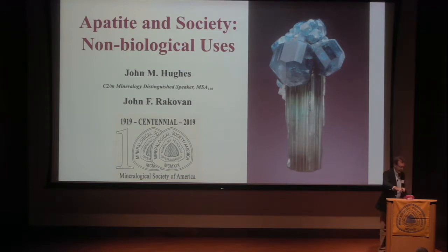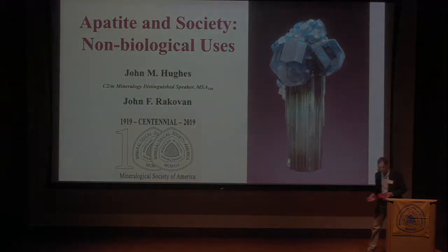We also have something that Joe Pasteris will talk about in a little more detail, but I'll just mention this. This is a prosthetic eyeball. It was made from coral, calcium carbonate, but was replaced by apatite. And what's amazing about this is because it's apatite, and when it's put into the ocular cavity, it's recognized by the body, and muscle will grow into it, and it will eventually track with your good eye. I think it's just an amazing example of the types of things that are happening today in biomaterials.